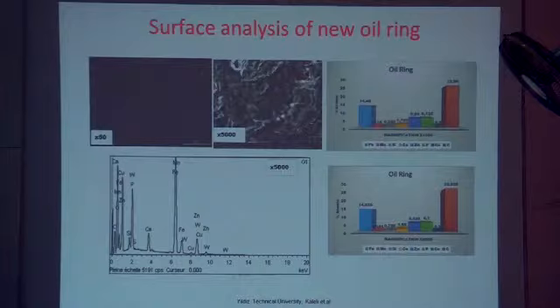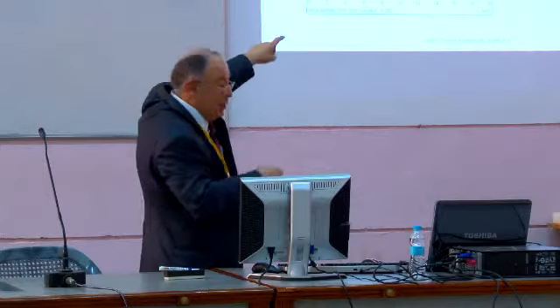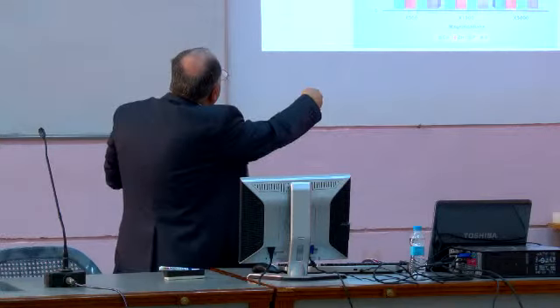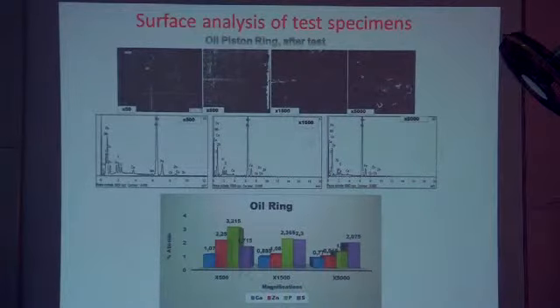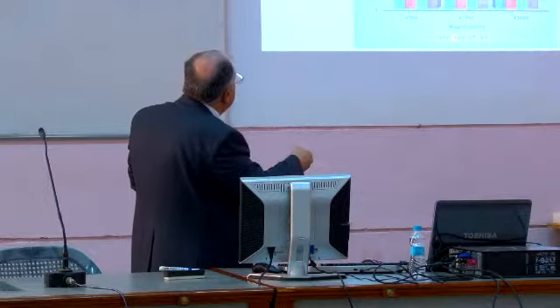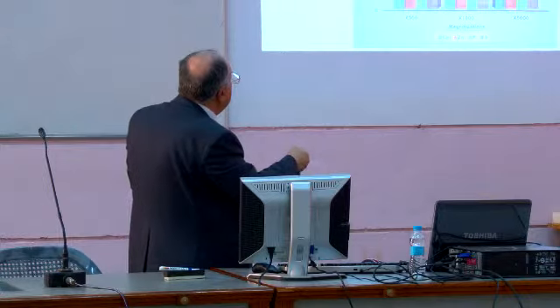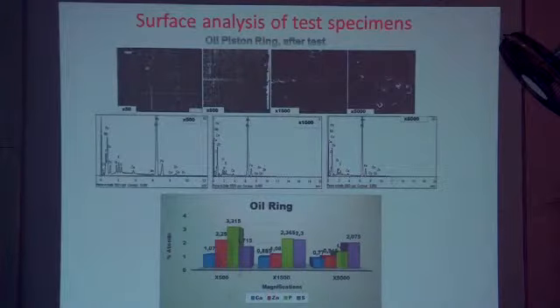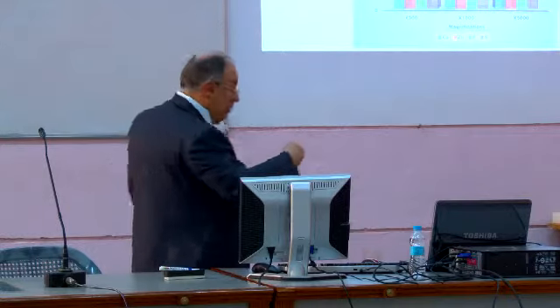Sorry, this is before the test - new piston rings, I'm sorry - and this is after the used test. Even after the test, in different magnification, we have all the additives like calcium, zinc, phosphorus. The calcium is very interesting because on the coating they also use calcium. There is an amount of calcium, but this can also come from the lubricant.